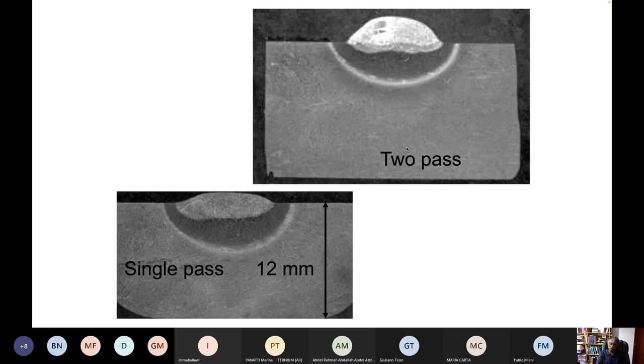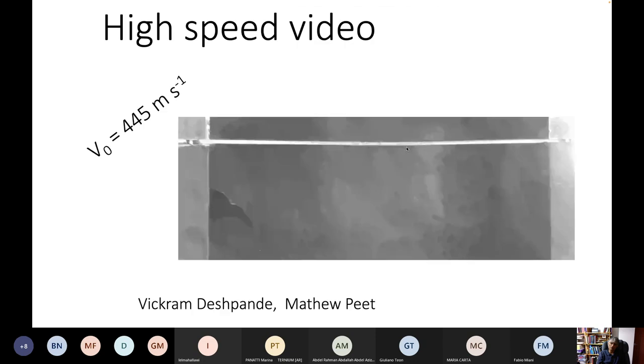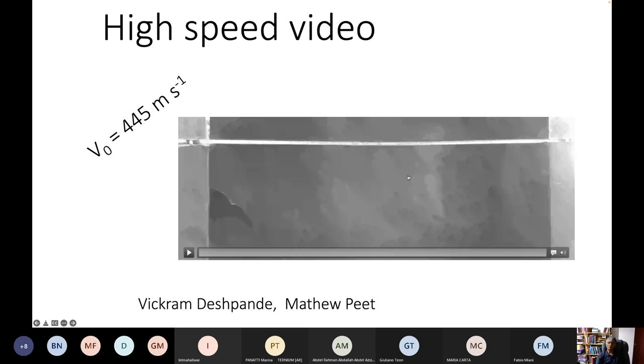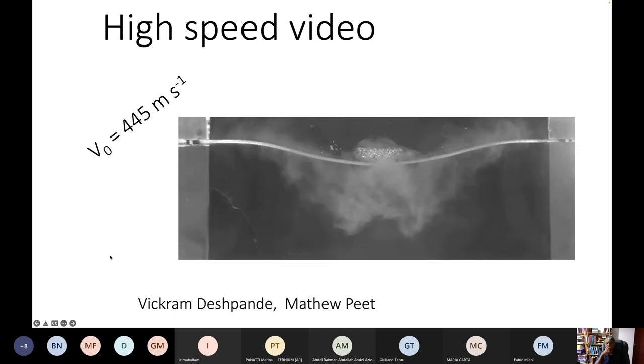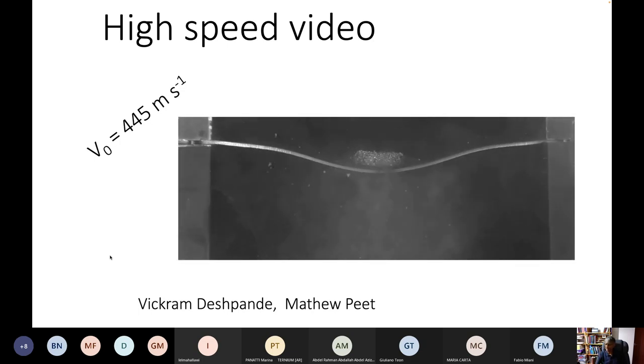We have two applications we are looking at. One is a blast-resistant steel. A blast means a sudden distributed load — it's not like ballistic where you have a projectile hitting the armor. In the laboratory we test by firing a high-velocity aluminum foam onto the steel, and then we see how much it deflects and whether it breaks. There is a movie showing this. The material survived the test for blast resistance.